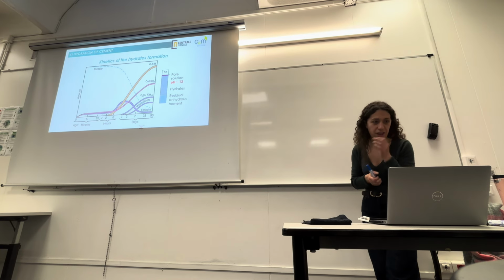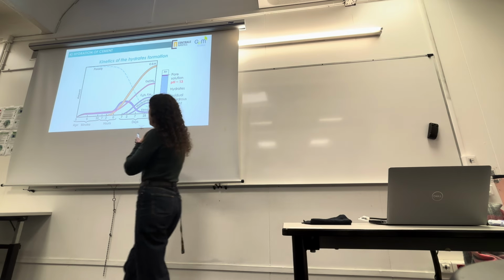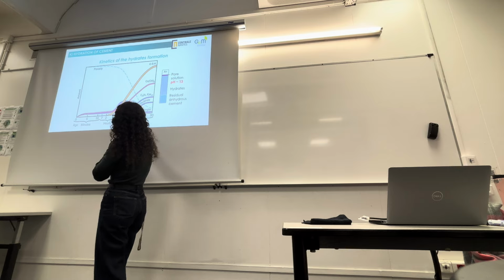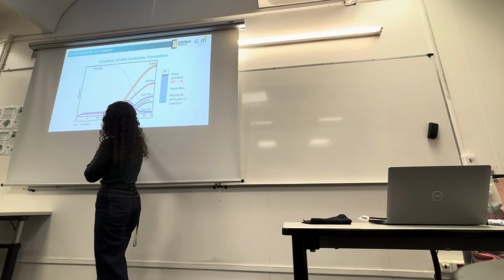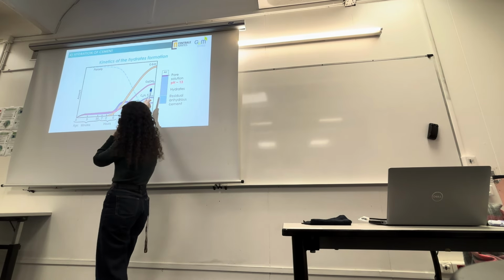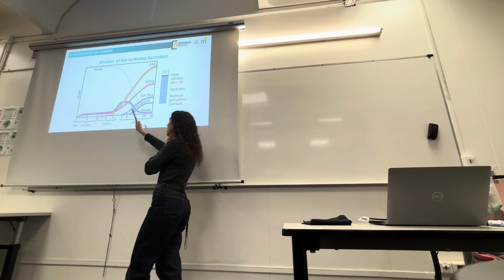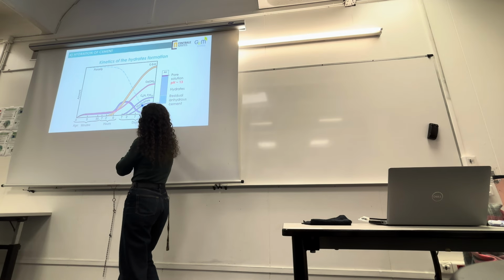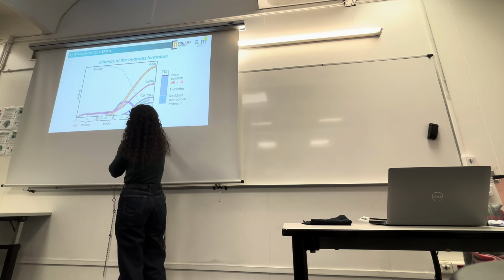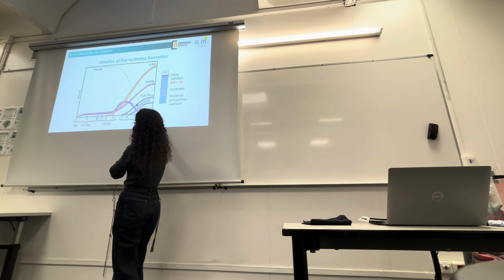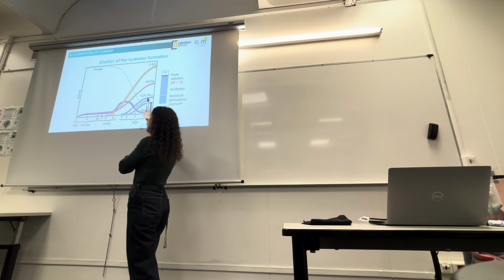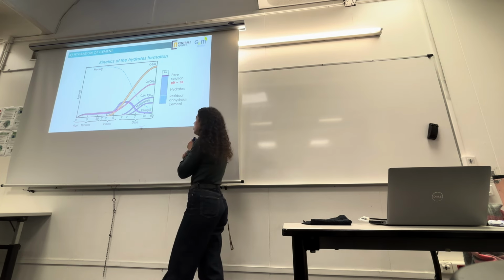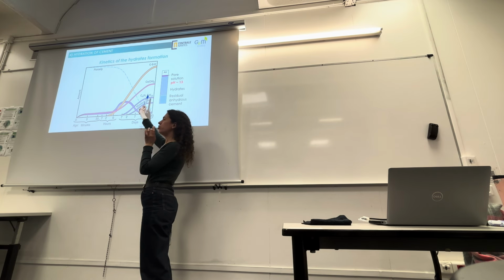Okay, so now we have the kinetics of the hydrate formations. In the first minute, you will precipitate, yes, it turns out we precipitate after a few hours. And you have CSH, and hydrogarnet. And monosulfate will precipitate once you see the ettringite will decline, and then you have the precipitation of monosulfate and also hydrogarnet that will precipitate with the monosulfate. So I'm not sure if it's hydrogarnet. Just remember it is the form from the hydration of C4AF.